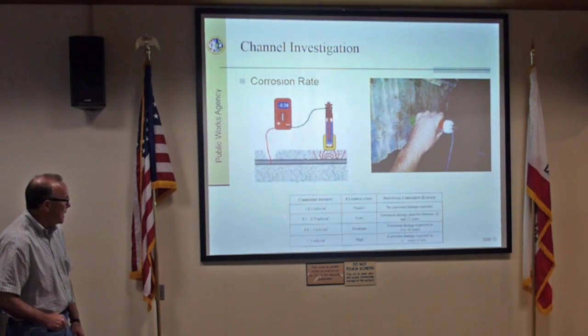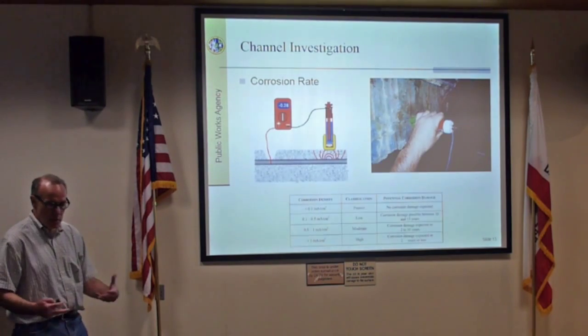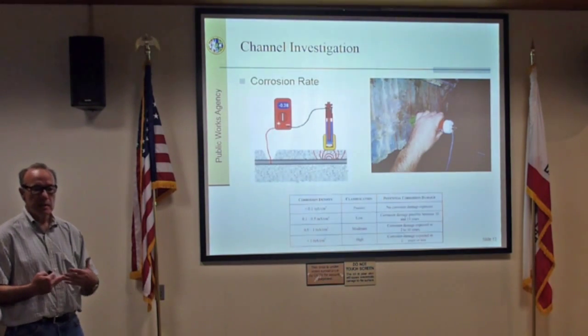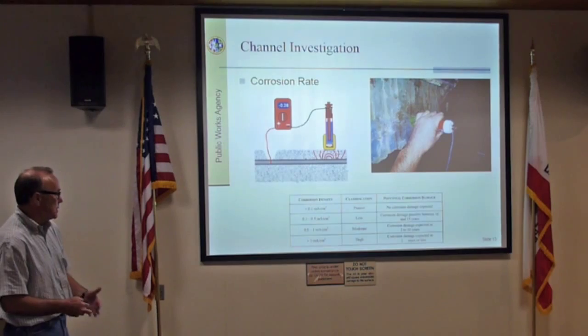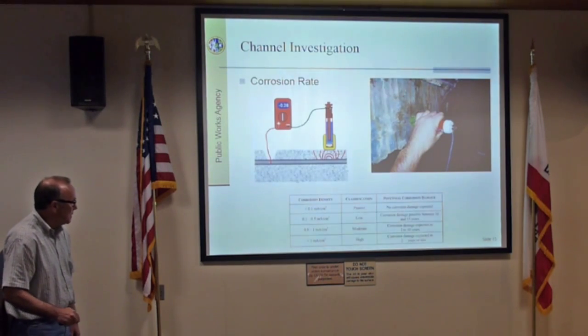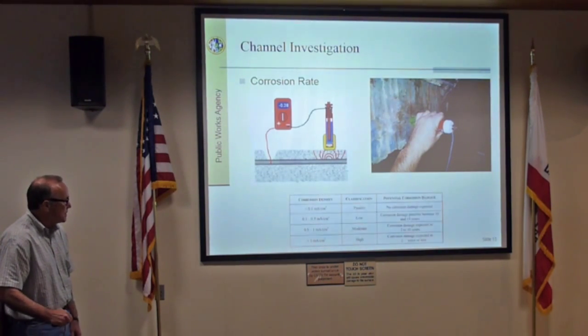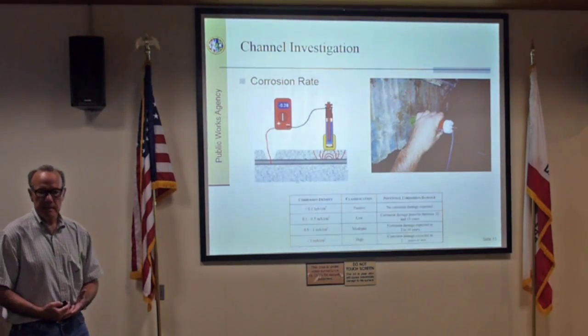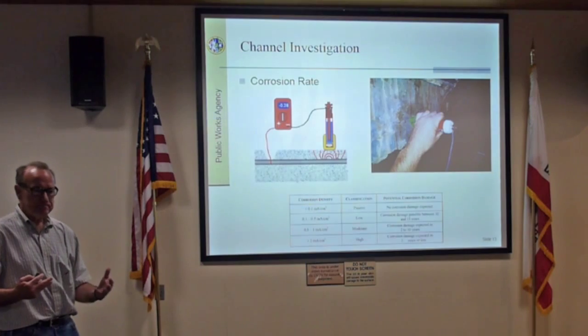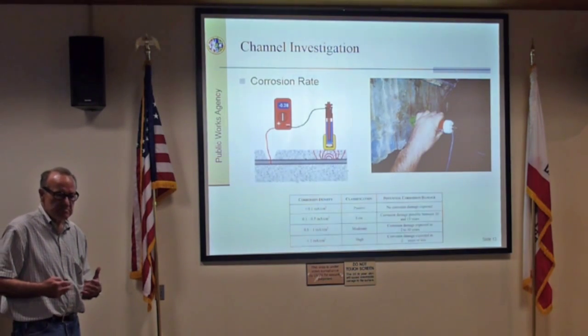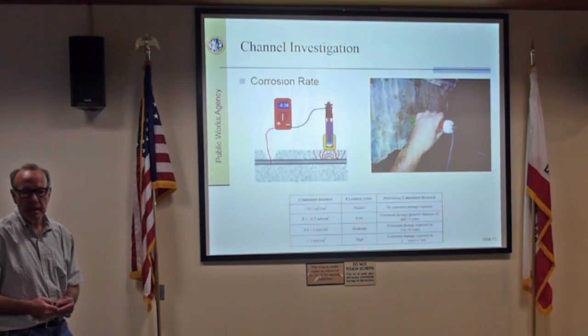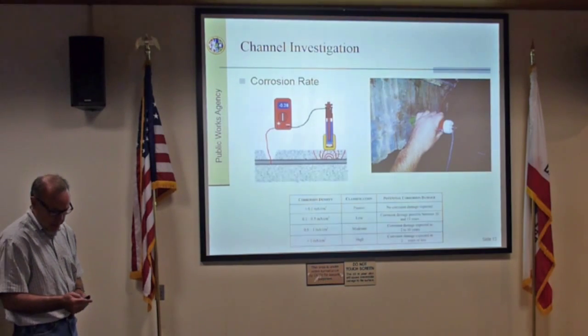Now, there's also a test where we use a corrosion rate device, and it will tell us what the actual rate of corrosion is. In that case, the device gives us some indication of what life expectancy we have in the steel. The test is good, but it can be misleading at times.